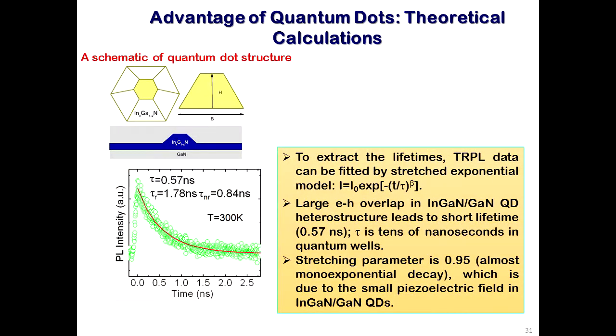So one of the first things we did was to measure the lifetimes. And so we started growing self-organized dots. I had about 20 years of experience in growing self-organized indium arsenide quantum dots, which are now being inserted in commercial lasers and amplifiers and so on. So we knew how to grow, although it wasn't that trivial to grow nitride quantum dots. But anyway, we started growing them, and I'll show you micrographs of those. We measured the lifetimes, and indeed our lifetimes agreed exactly with what was being calculated, and they were indeed very, very small. So this is what got us started a few years ago,